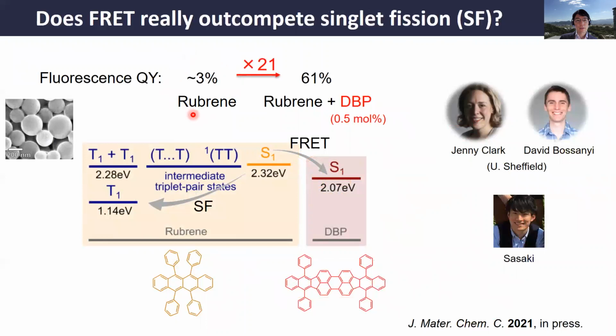Our rubrene nanoparticle shows a poor fluorescence quantum yield of 3%. And by just adding this third component DBP, we could improve the fluorescence quantum yield by more than 20 times, and it becomes 61%. And FRET is definitely happening, judging from the fluorescence spectrum. But the question is whether it outcompetes singlet fission or not.